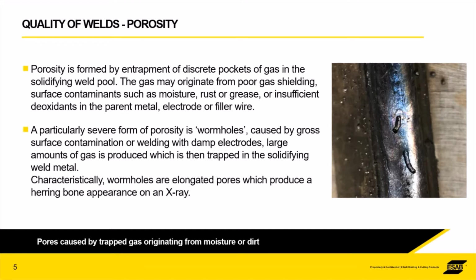The gas can originate from the shielding gas. If the shielding gas is not set correctly, it's the wrong size nozzle for the amount of gas that you're putting through, or even the gas has got moisture in it, which I've seen several times. It's fairly obvious that when you're welding, everything needs to be clean, rust-free, grease-free. Organic contaminants like that are probably some of the main sources of the problem. And additionally, damp electrodes. So not just dirt, but they don't want to be wet, and the workpiece that you're welding doesn't want to be wet, unless you're welding underwater. But that's another whole host of problems that we can talk about in another presentation. So what we're trying to achieve is nice, clean welds with nice, clean filler metal.